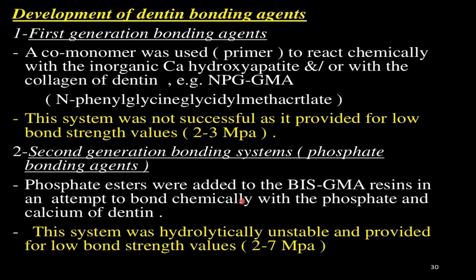Phosphate esters were added to the bis-GMA resins in an attempt to bond chemically with the phosphate and calcium of dentin. This system was hydrolytically unstable and provided low bond strength values, 2 to 7 MPa.